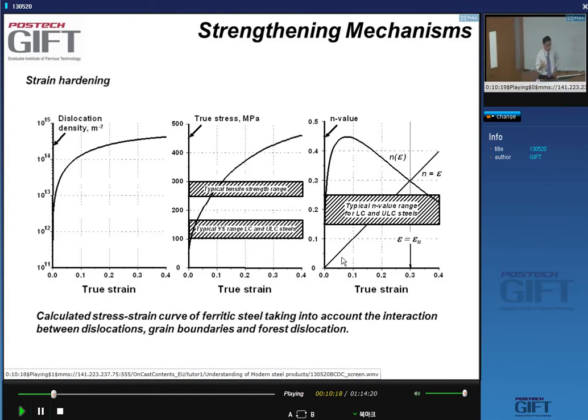Now you can model this, and it's in the book if you're interested in the details of the theory. So you can model this strain hardening mechanism nicely, and calculate stress strain curves based on dislocation density evolution, and then you can also calculate as a consequence the strain hardening value. Strain hardening in the meaning of the exponent in the Hollomon equation. So you know that you can write stress is proportional to strain to a certain power. You call this the strain hardening.